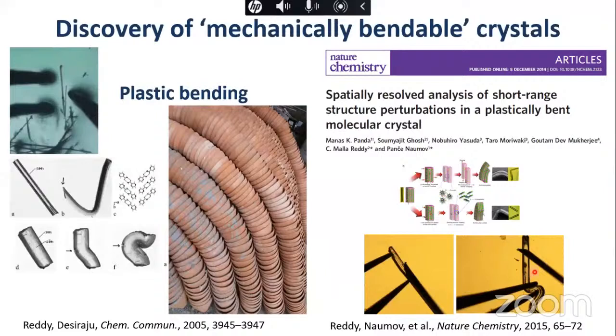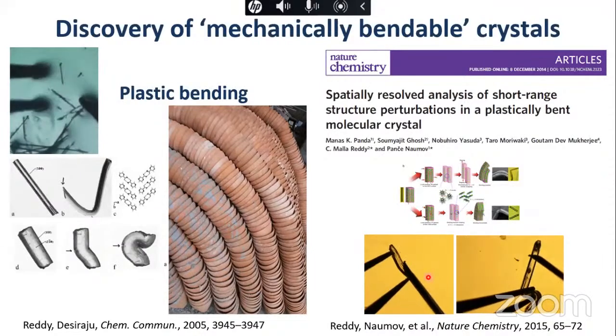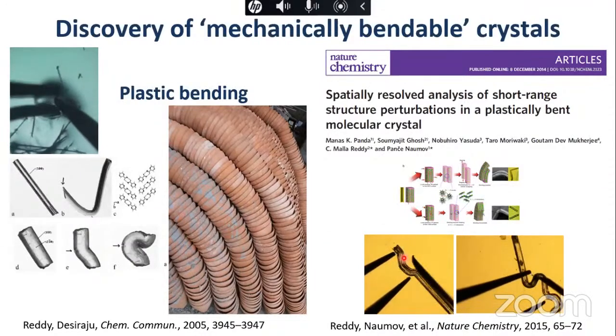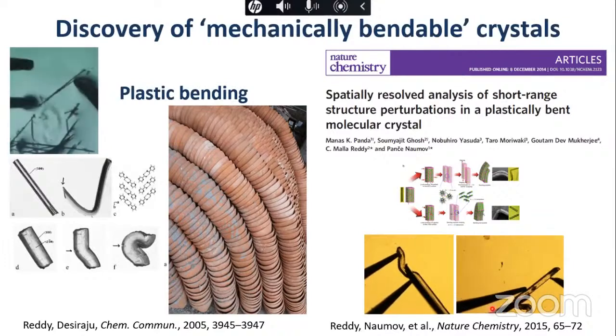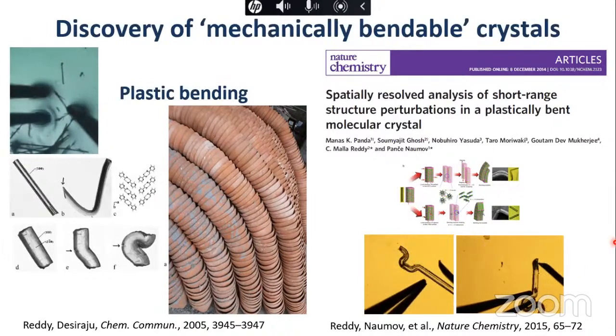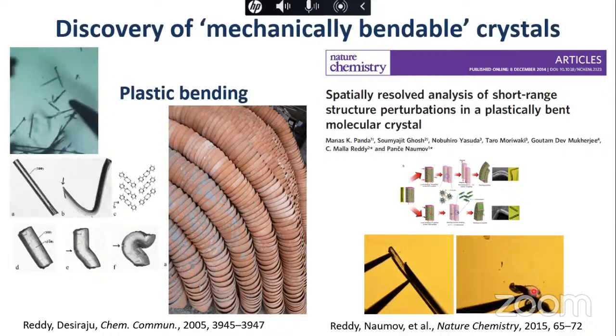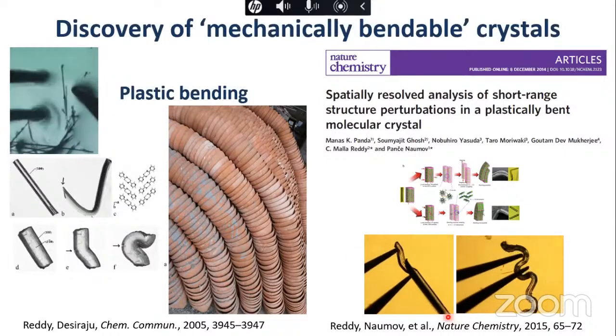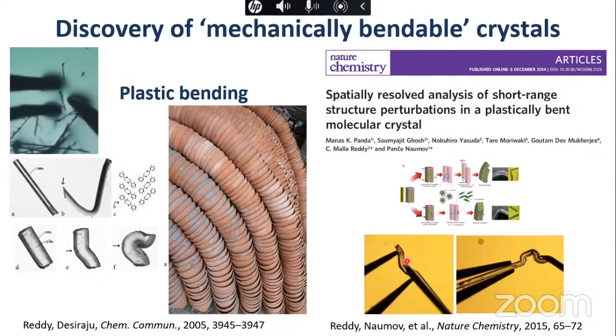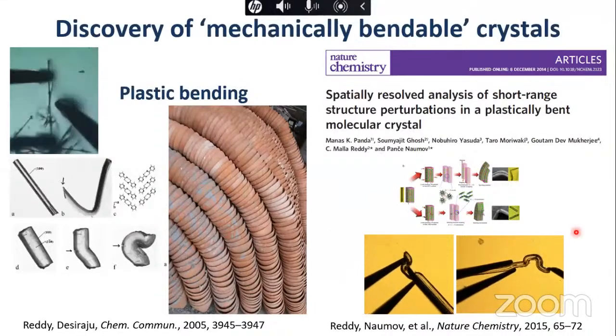For example, as you can see here, this is a hexachlorobenzene crystal, so you can nicely bend them, and this is a plastic crystal. The packing, if you see, you have stacks which are running along this axis, and between the stacks you have weak interactions as shown here.